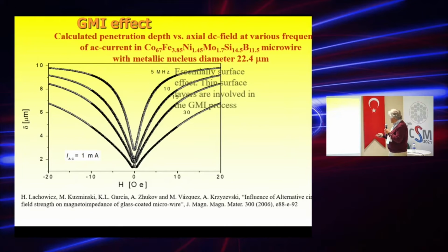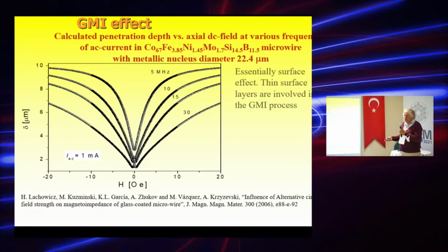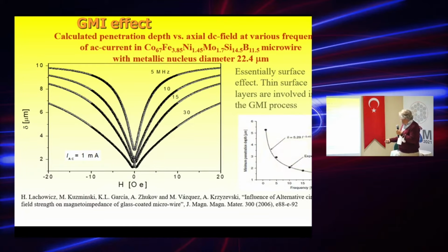I mentioned that this is essentially a surface effect. This is the calculated dependence of the skin penetration depth on magnetic field. You can see the change is quite large, from about 1 micrometer, for this 22 micrometer diameter microwire, to less than 1 micrometer, and then growing up to a few micrometers. So it is field dependent. If you now plot the minimum skin depth versus frequency, you can see that it decreases with the frequency.